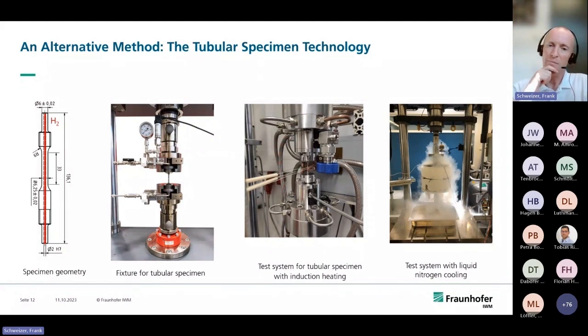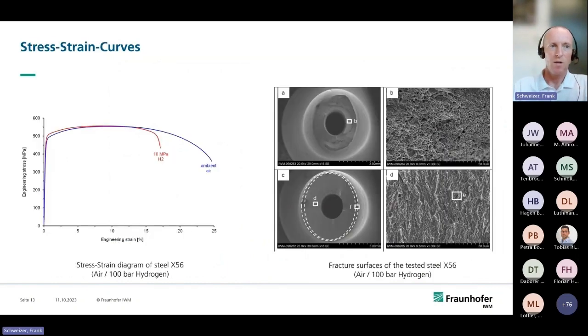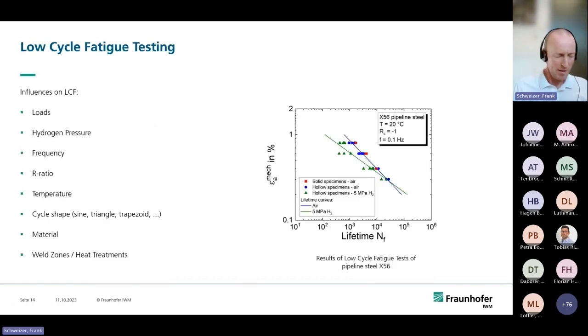Also in the project, we used that to measure the fatigue properties, which is not so easy in these autoclave systems. So also you see here stress strain curves with the hollow samples. You also see the reduction by 100 bar hydrogen, and you can also have a look at the fracture surfaces, and you see a change from ambient air with a ductile behavior to a more pronounced fracture surface with hydrogen. So as I said, the main thing is these inner bore samples.